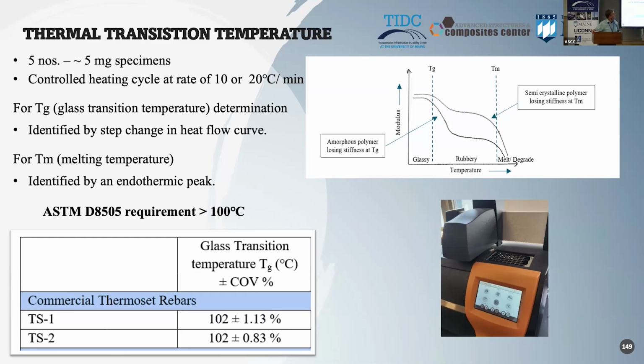The second temperature that is important once we go from glassy to rubbery and we continue increasing the temperature is the melt temperature. And the melt temperature is where we finally lose all the remaining stiffness. For the semi-crystalline, it will mean those islands, those pockets where the molecules were aligned, now they become completely randomized, no more crystalline structure there. If we go further, we will degrade the material.